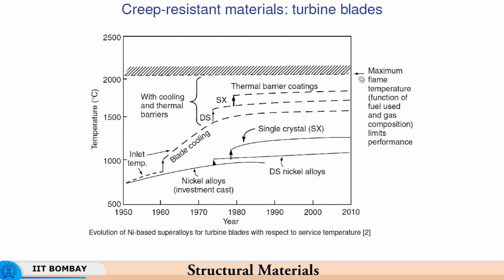So, if you look at this, if this is a maximum flame temperature, then the flame temperature which is below, which is inside the blade with cooling and thermal barrier coating is quite substantially reduced as compared to the temperature that would otherwise be present. Now, blade cooling is often done using what is called as micro channels which are produced inside the blade. So, turbine blades have micro channels through which the coolant fluid is made to flow and take away the heat from the turbine blade. So, lower is the temperature of the turbine blade, lesser is the propensity for oxidation, as well as higher is the strength of the turbine blade.